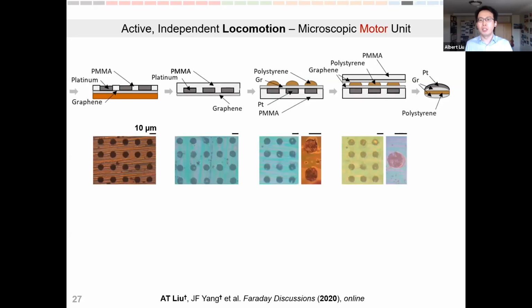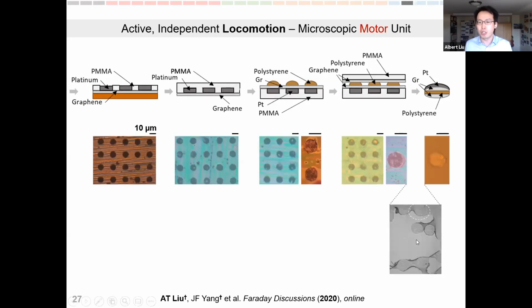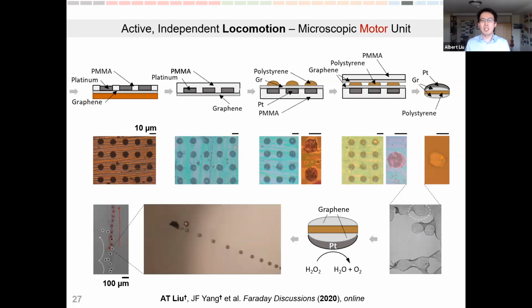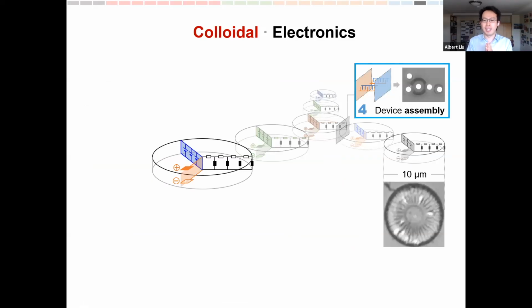As a result, after autoperforation of the two-dimensional material, this gave us a cell-sized particle that is not only encapsulated by graphene from top and bottom, but also has this asymmetric layer of platinum coated onto the graphene material. Now, this simple addition of the platinum patch actually introduced a useful function. In this case, we're building a locomotion module into our particle because platinum is known to decompose hydrogen peroxide, making oxygen bubbles. And then we can use the bubble as a propulsion method to propel our particles forward. Finally, we have access to locomotion.